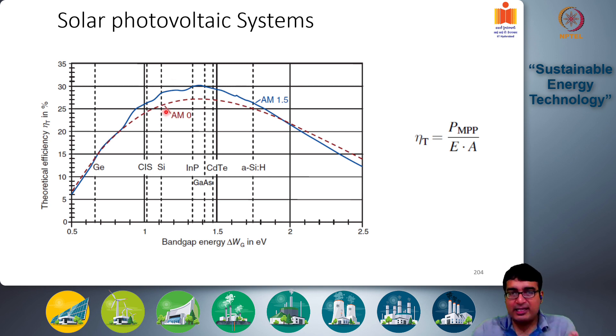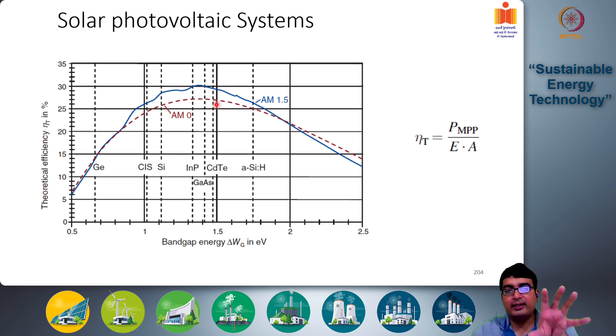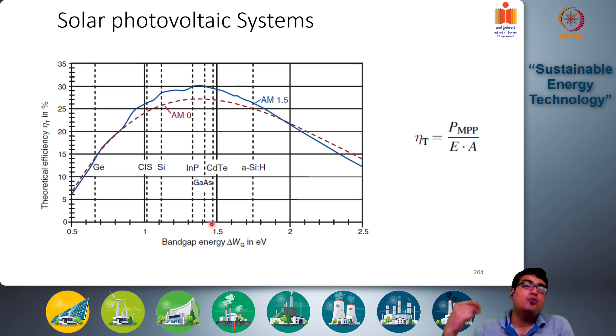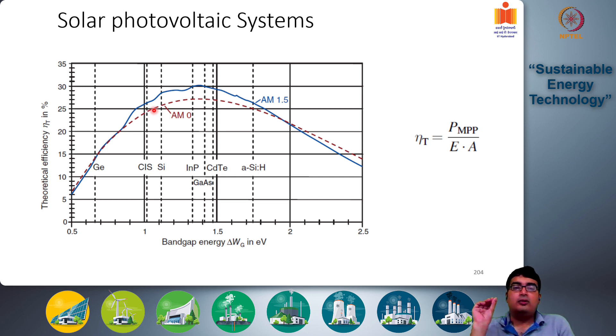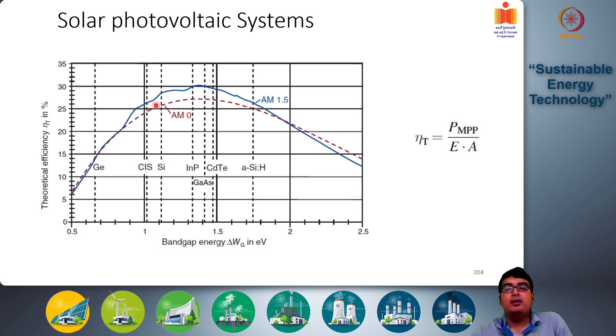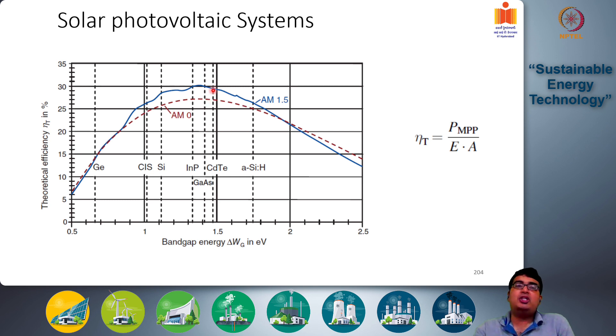Silicon does not suffer as much. You get a slightly skewed distribution with maximum efficiencies for band gaps of around 1.4 electron volts rather than 1.1 electron volts for silicon. Still, silicon has reasonably good efficiencies of around 28 percent for AM1.5 radiation and 26 percent for AM0 radiation. Using indium phosphide, gallium arsenide, and cadmium telluride systems, you can reach 26 to 27 percent for AM0 and 30 percent for AM1.5.